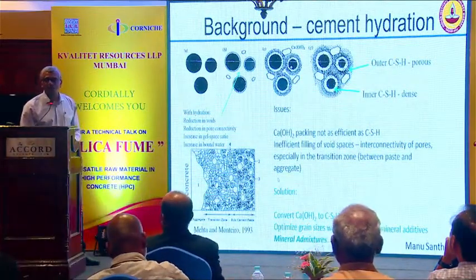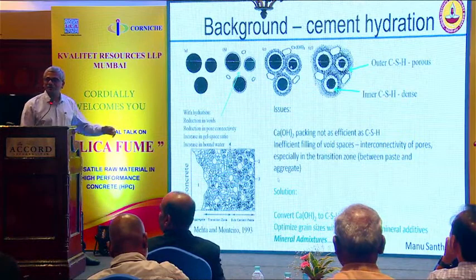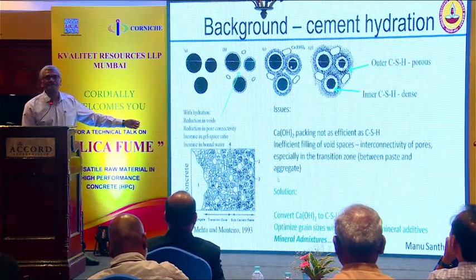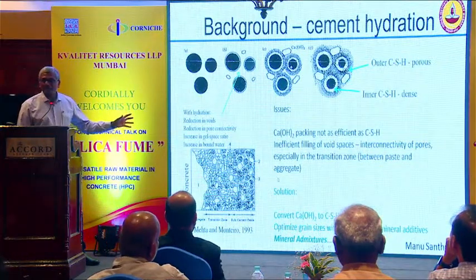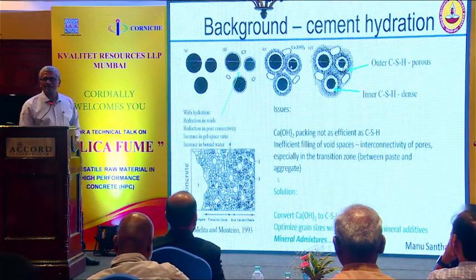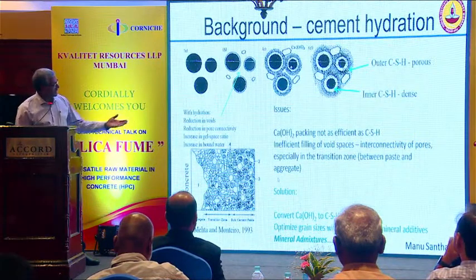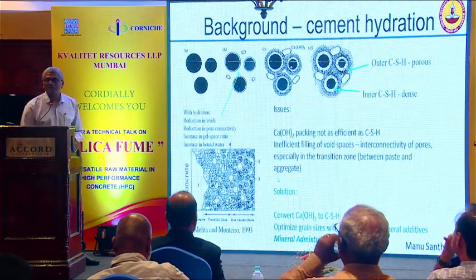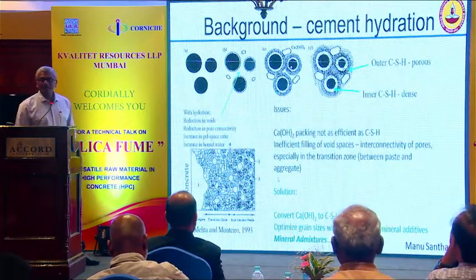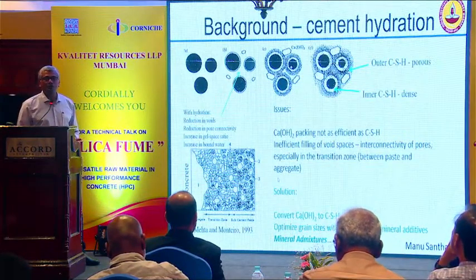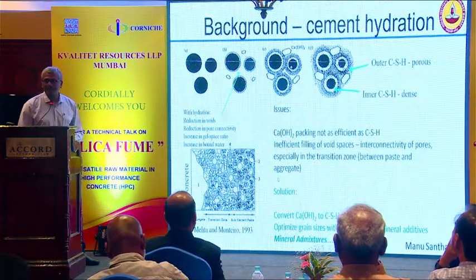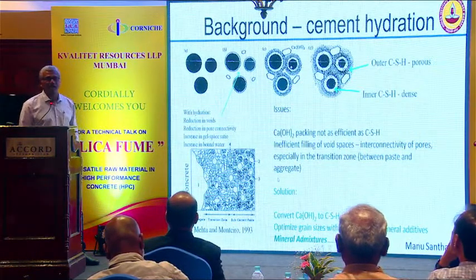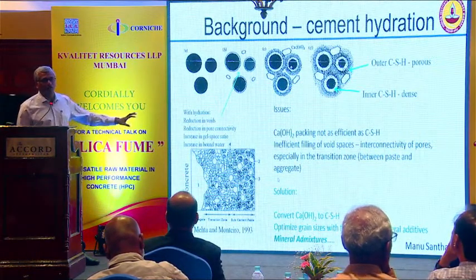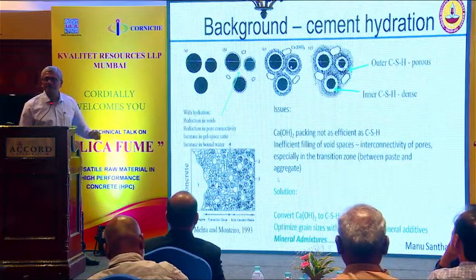It begins at a very low level of load, and that cracking is further worsened because there's more porosity available in the ITZ. So the packing of the products in the ITZ is not as efficient, and secondly, pores are not filled up properly. Because of this, we generally tend to use what we call mineral admixtures. Any mineral admixture like fly ash or slag or silica fume will do a good job of trying to fill up the space around the aggregate and densifying the interfacial transition zone.